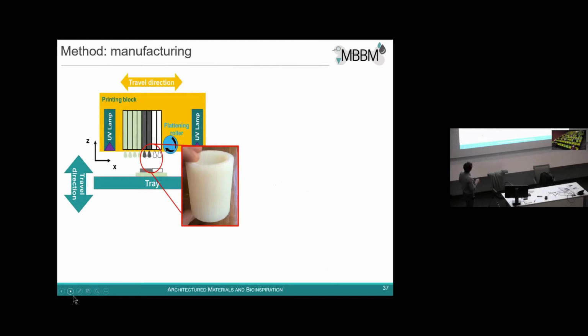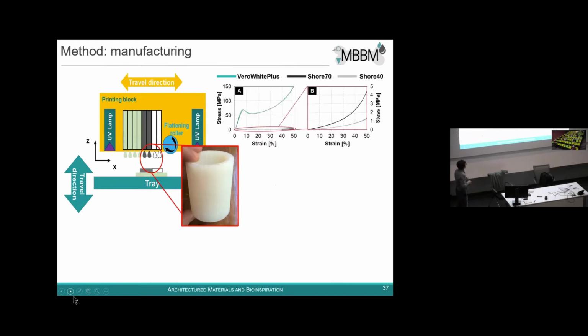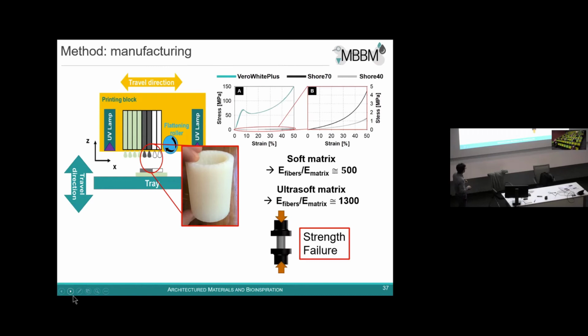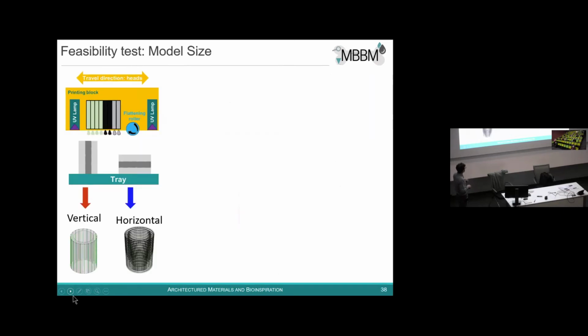So we 3D printed this, and we consider actually stiff fibers. The fibers that we inserted are about 2.5 gigapascal, and we consider 2 types of matrix such that the elastic contrast between fibers and matrix is a factor of 500 or more than a factor of 1000. So what we call soft matrix or ultra soft matrix. The matrix is an elastomeric matrix, and the fibers are glassy rigid polymers. And then we performed some mechanical tests to failure, and we explored a little bit the behavior of the system.